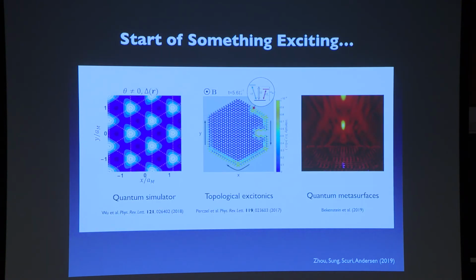So these, without going into detail, are the kind of things that we are now trying to do by making those arrays as nice as possible and start to trap electrons and excitons and holes into particular spatial patterns. It turns out, according to the theoretical calculations, that you can actually use those resources to make quantum simulators, because you can generate exciton arrays, and those excitons are interacting with each other through their dipole moments. And then, as Vladan Vuletić here at MIT and Misha Lukin, my colleague at Harvard, have shown, you can use those resources to generate so-called quantum simulators, a primitive version of quantum computers. We can also use those resources to generate so-called topological excitonics and metasurfaces.